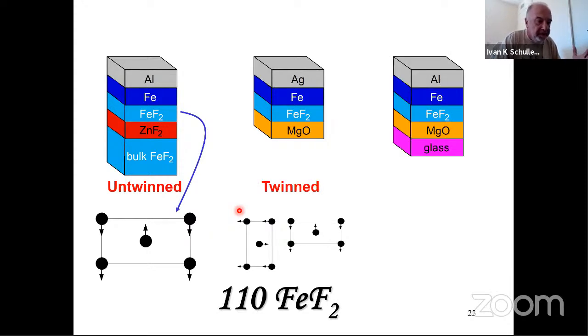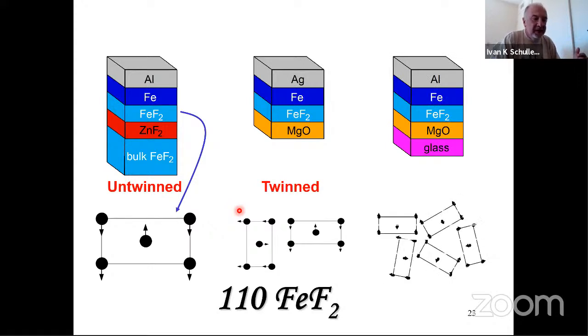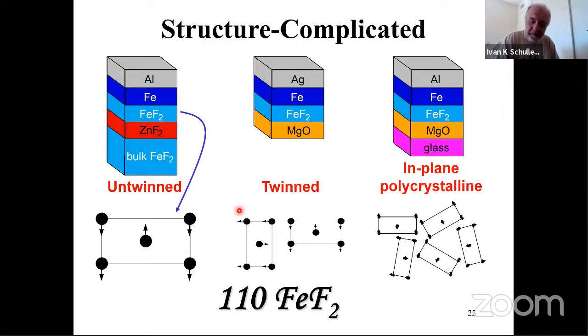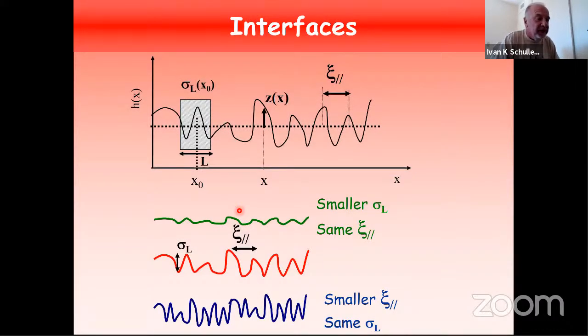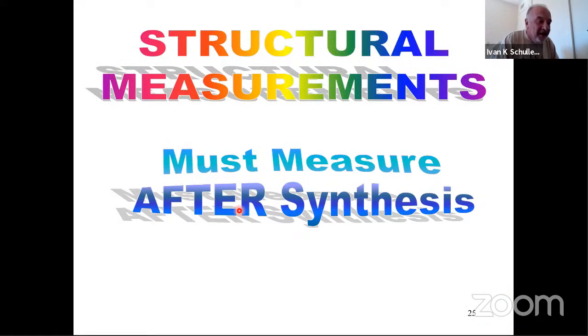If, instead of growing it on top of magnesium oxide, you grow it on glass, then you get all kinds of orientations. They are still 110 oriented perpendicular to the layer. However, in the plane, they are random. And each one of these crystallites in the plane has different properties. So the structure is complicated. It's not simple in all these materials that we make with these very fancy kinds of techniques. The other thing is that the interfaces are not perfectly flat like people would like you to believe. So at the interfaces, there is roughness and all kinds of complications that you have to worry about. You cannot forget it. So structural measurements are important, and you must measure the structure after the synthesis, not before the synthesis. So you synthesize the material, you have to measure it, and measure it quantitatively.